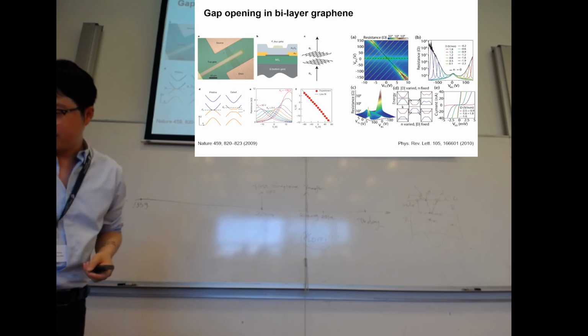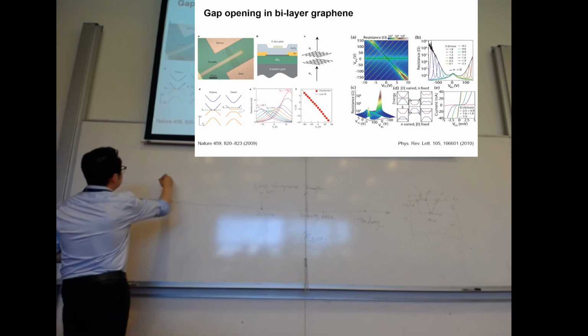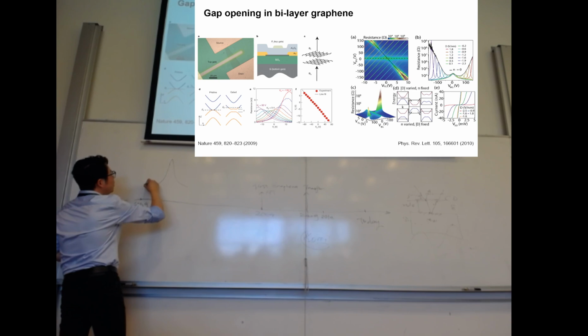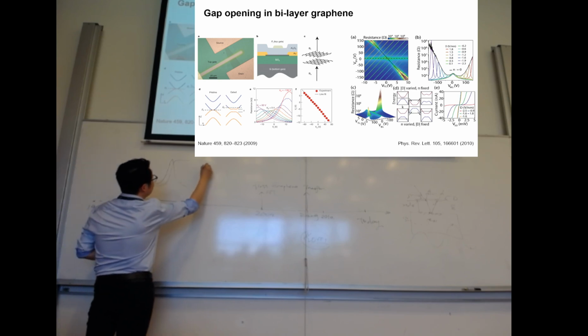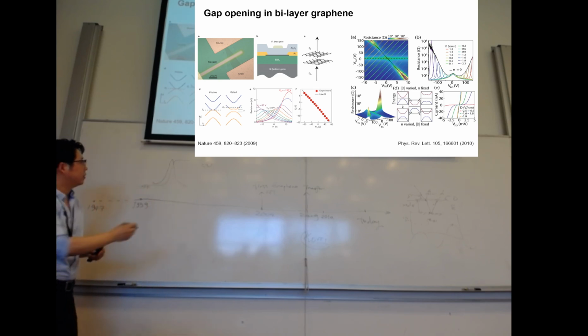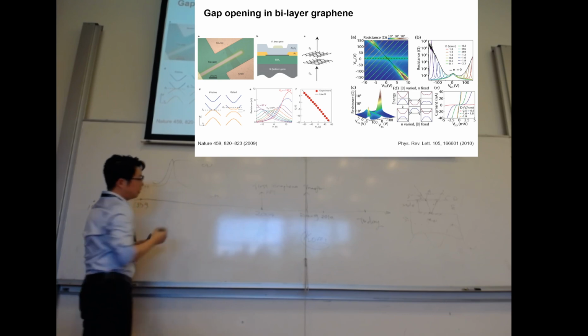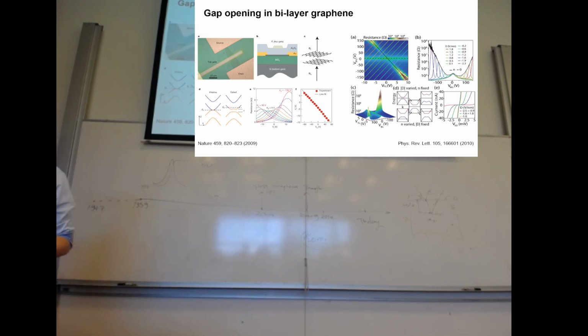We want, instead of a peak, we really want some kind of off and on structure like this one. The x-axis is carrier density. So still, graphene can be gapped in terms of vertical electrical field applied to bilayer system, but the gap is not very well formed for application purposes.